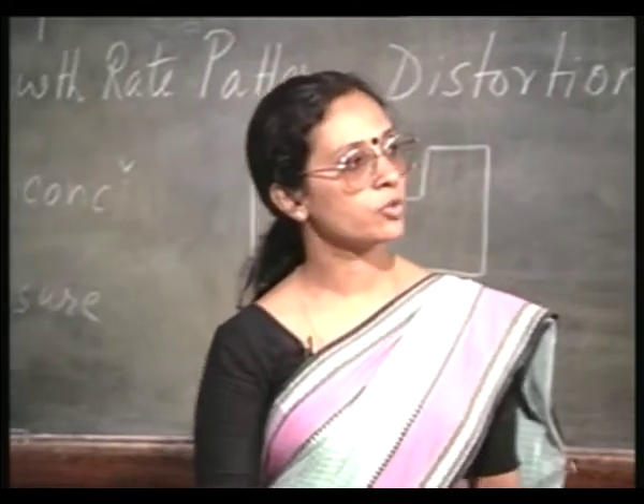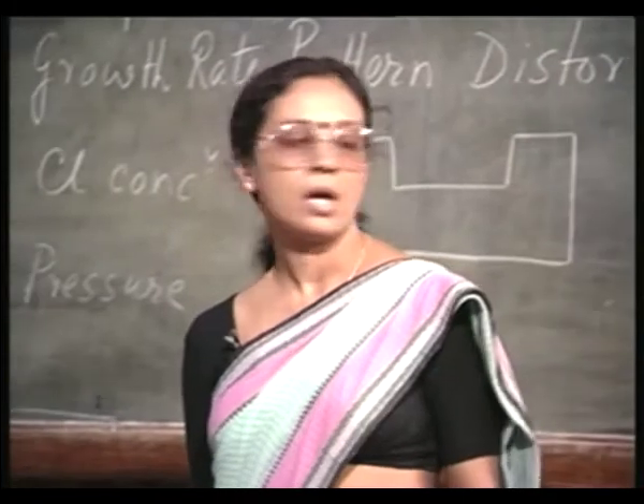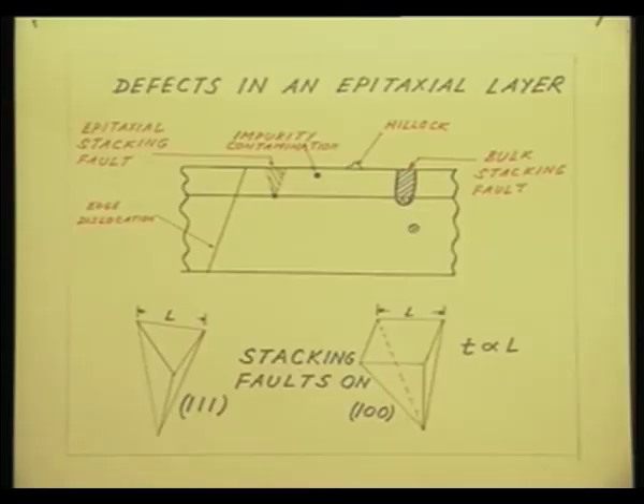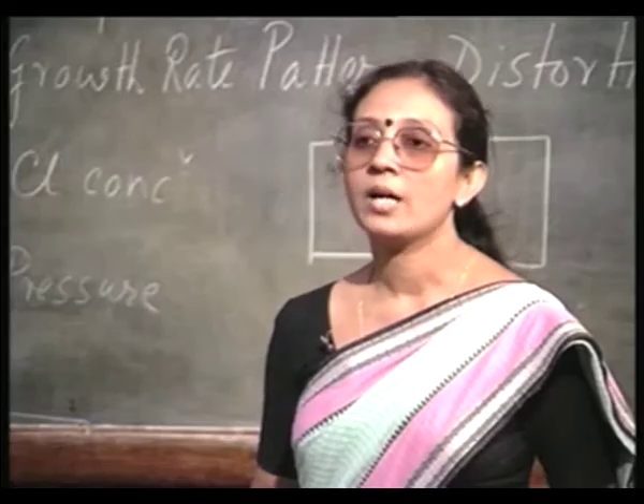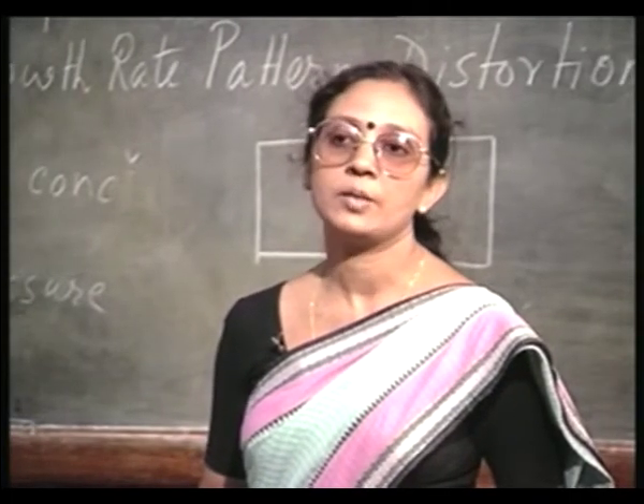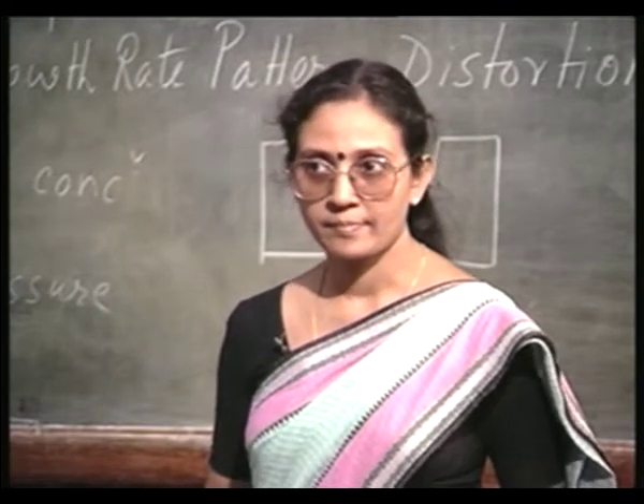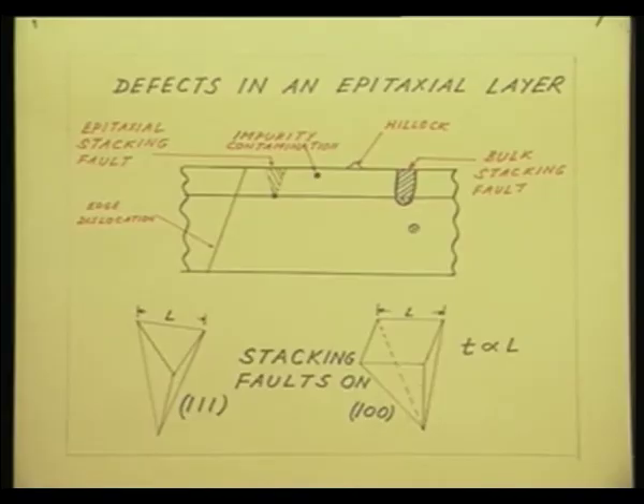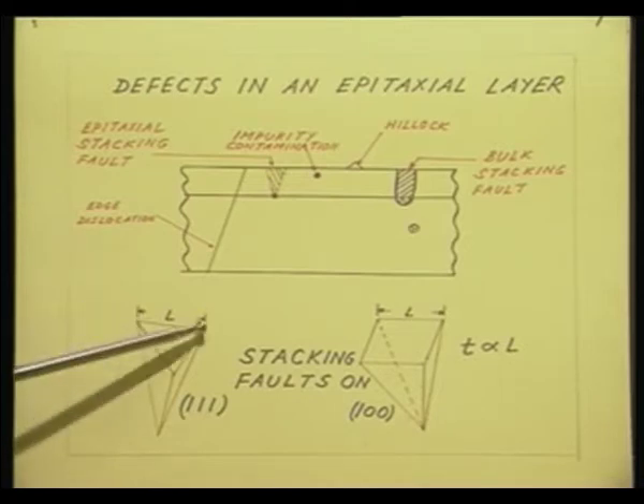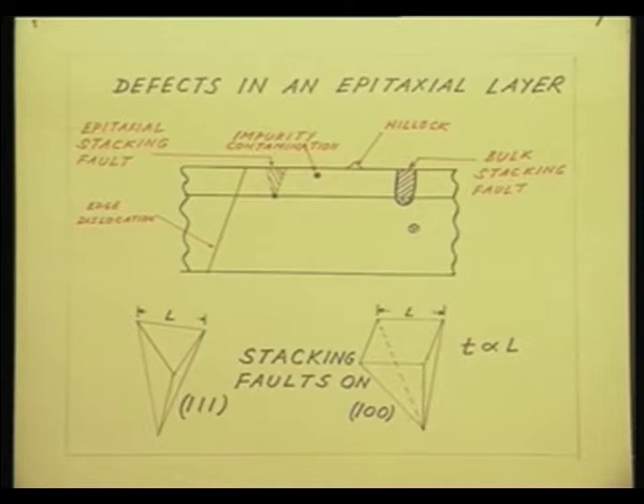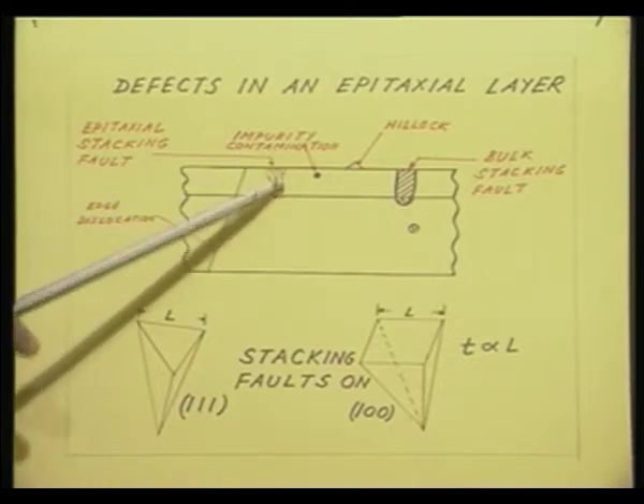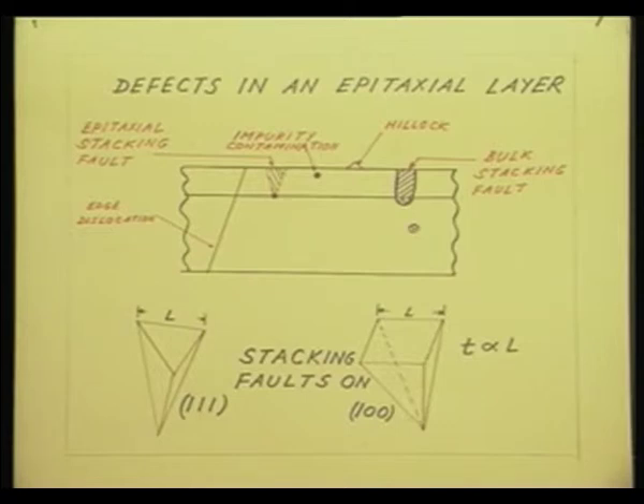The hillocks can of course be viewed without etching. There is a good fallout of these stacking faults provided they are within reasonable limits. The good fallout is that this offers a way of measuring the thickness of the epitaxial layer. This is again by geometric consideration. You see, what you have exposed here is an equilateral triangle and then it goes into the pyramid. So, actually the height of this pyramid is your epitaxial layer thickness. It is extending all the way down to the substrate point, is it not?